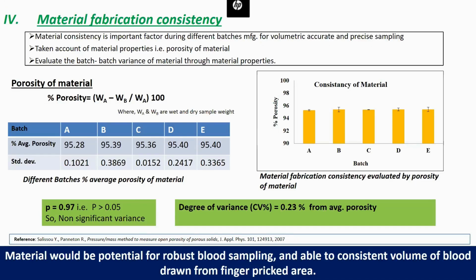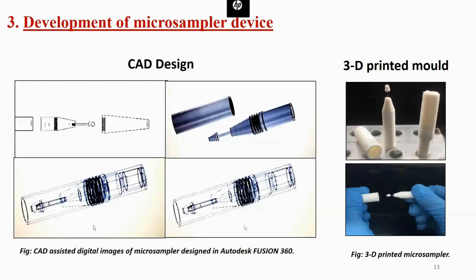Then we checked the material fabrication consistency. For scalable production, we need the matrix to be produced with good consistency, and porosity is one important factor. We found that in the 5 batches we tested, the porosity was quite consistent with the parameters which we had optimized. Then we converted this matrix into a usable device using CAD design and 3D printing. You can see on the right-hand side the 3D printed microsampler device.